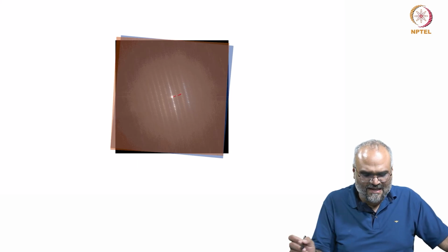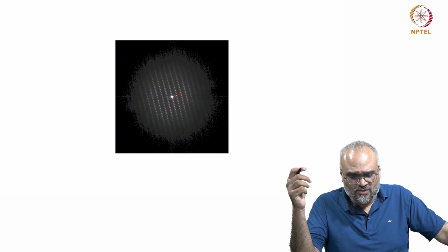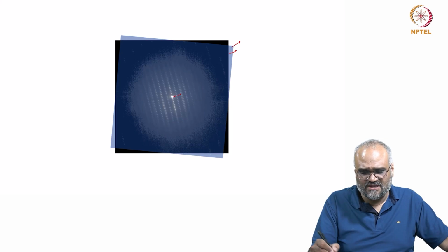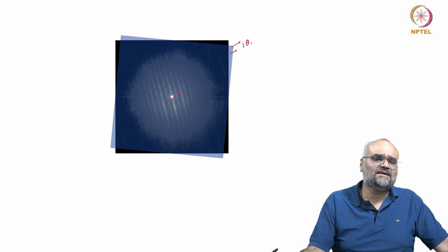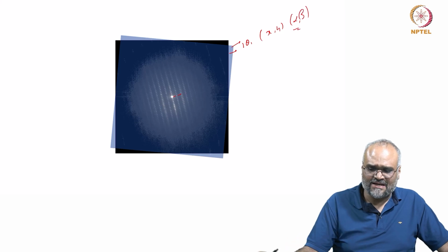So, you can see the common axis is overlaid and it remains common with all the others, and the third diffraction pattern would actually be like this. So, I have the 3 varying D1, D2 and D3 values which are lying here. Now, from this, how do I construct a projection of a unit cell becomes the question. If I say that to go from this reflection to this reflection, I should have misoriented my crystal through an angle, say theta 1, which I can determine from my x, y tilt or alpha beta tilt from the microscope.